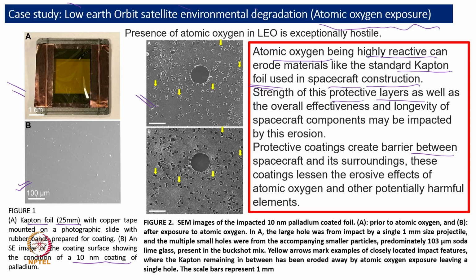In this case particularly, the projectile, a particle which is getting impinged on the surface, is roughly 1 mm in size, and it is creating this one big hole. The small holes are because of the other particles or other projectiles, which are roughly 100 micron soda lime glass particles, assuming these will be the particles in the environment when there is some sort of debris. They are treating the 1 mm projectile as debris, and the 100 micron soda lime as debris, which remains in the environment.